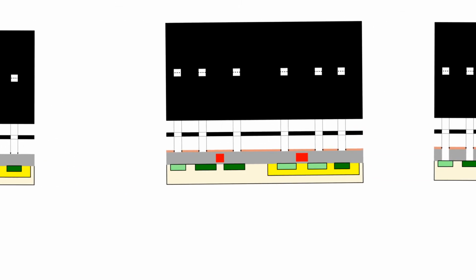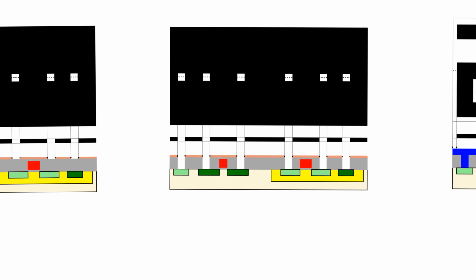Then we apply photoresist, we expose the photoresist, and we develop the photoresist. The areas with the small transparent squares are obviously going to be contacts. They're going to be areas where the metal wires are going to make a dive down to make contact with the N plus and P plus areas. So we have to etch the silicon dioxide under the developed photoresist. So we are going to use wet etching to open contacts through the silicon dioxide.